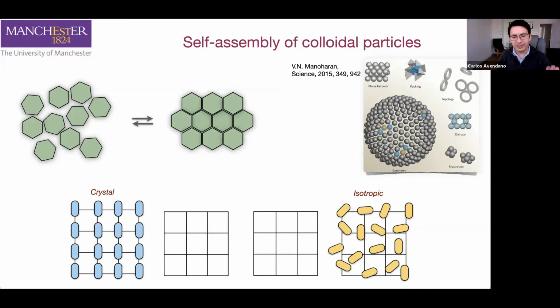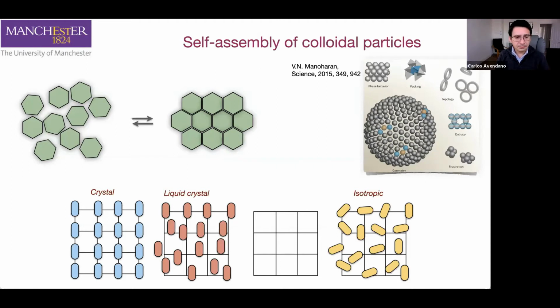In this case, the centers of mass of each of the particles are localized in specific lattice sites. And we can see that the orientations of all the particles are also well defined. However, there are several systems, particularly when we talk about non-spherical particles, that can exhibit some structures that are in between the isotropic and the crystal phase. Some examples are liquid crystals, in which there is no translational order. So the centers of mass of the particles can be in any location within the sample, but on average, the particles are oriented in a given direction.